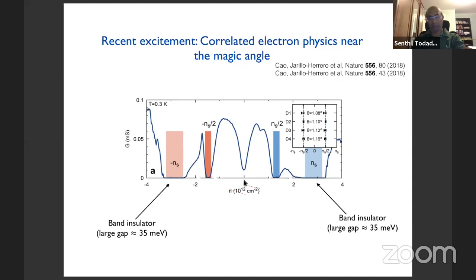And likewise, if you electron dope it, you go here, then you get to a regime where the conductance is once again gone to 0. Okay. Now, so these we understand or correspond to fillings at which the system is a band insulator. So this Moiré potential reconstructs the lattice, forms bands within this mini Brillouin zone. And this filling corresponds to a filling in which some sort of bands are fully occupied and the flat bands, which is this region, are fully empty. And likewise, this region corresponds to a situation in which you've occupied all the flat bands, but not any of the higher energy bands. Okay, and these insulators have big band gaps.